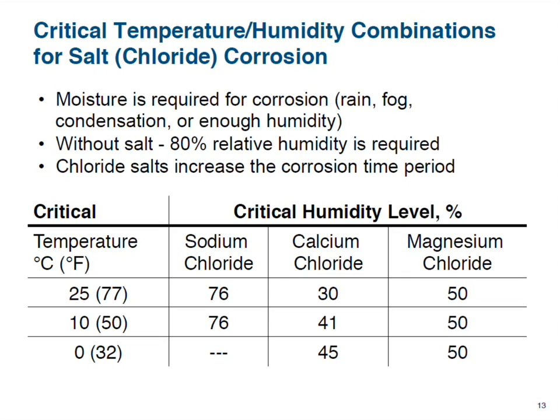We used to just use sodium chloride, rock salt, for de-icing. And when we only had that in the environment, which wasn't introduced until after the arch was built, you had to hit 76% humidity and 50 degrees Fahrenheit for that salt to be actively corrosive. Salts lower the humidity levels at which corrosion can occur, but spring rains would wash most of it away.